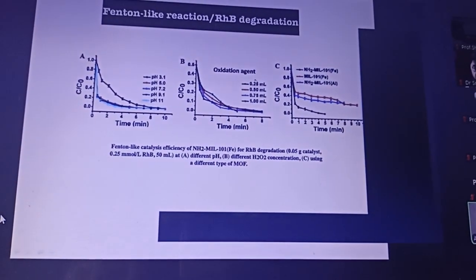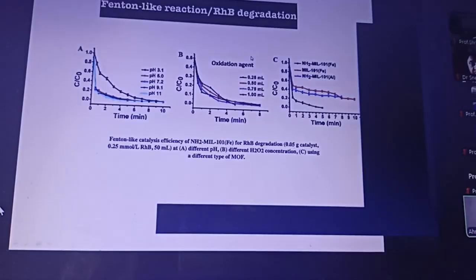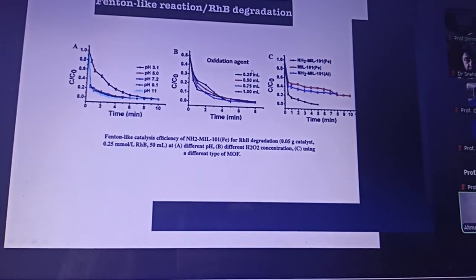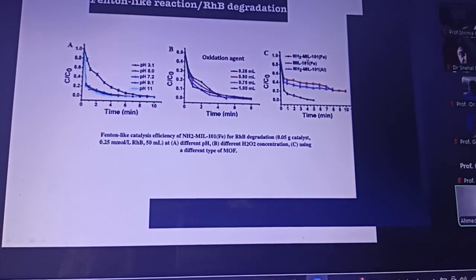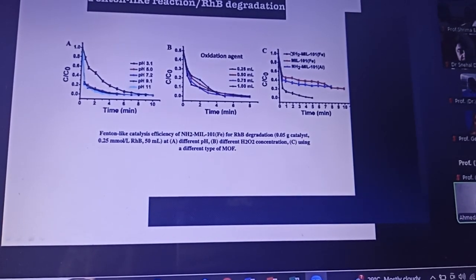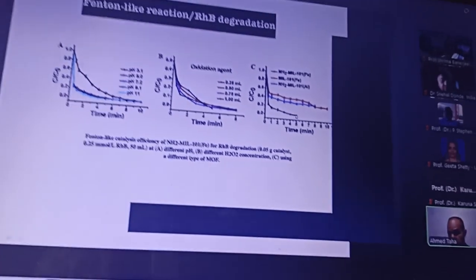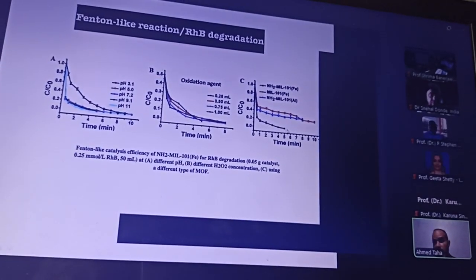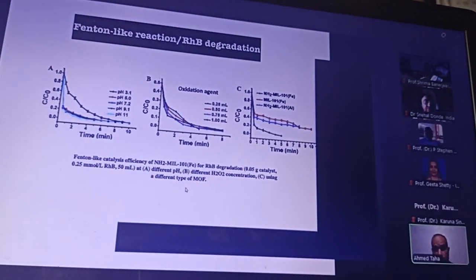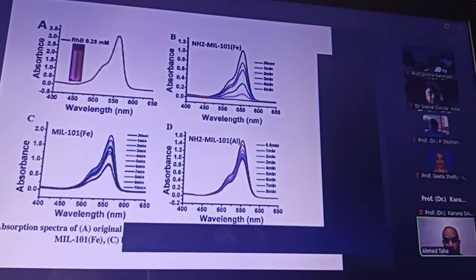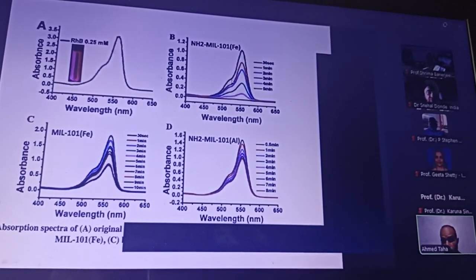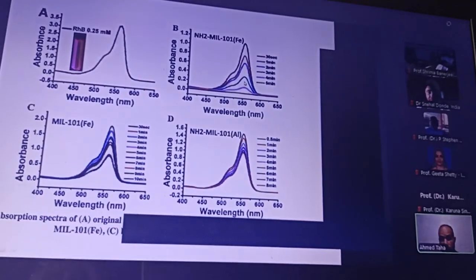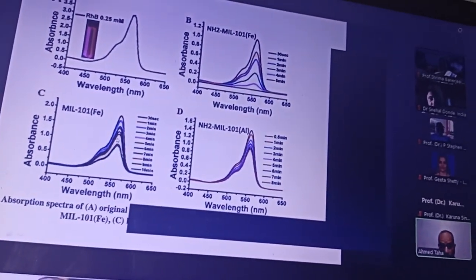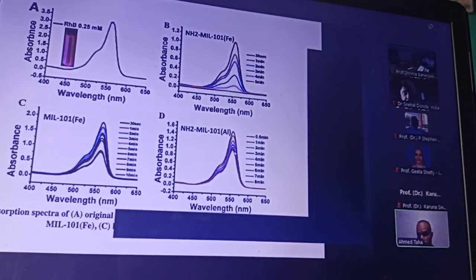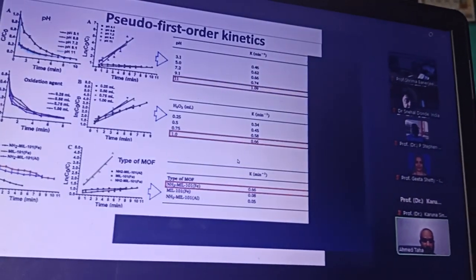And then we studied how much oxidation agent we need to add. We also compared the performance of the 3 materials we have, and we found the one with the amine and iron showing the best performance of complete degradation within about 5 minutes. And this is a visualization of the performance. As you see, in 5 minutes we can get rid of the dye, compared to the other material, where we still have a high concentration of the dye even after 8 or 10 minutes.